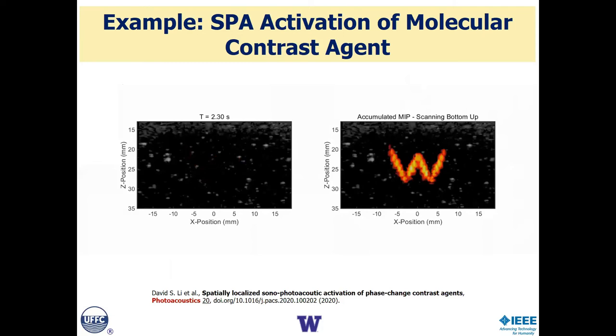I'll just show one image of these types of agents. This is work that comes from our lab in the last year or so, which is a new agent, which is activated with simultaneous light and acoustic excitation. And I won't go into details of the agent. What I will tell you is that this agent can be excited with light levels which are very low, well below a millijoule per centimeter squared, and acoustic pressures with mechanical index well below one, such that we can excite these agents at depths. As you see here, this is about 3 centimeters inside a tissue, and these agents are at picomolar concentration. We can go down to that low concentration. So true molecular imaging done with these nanoscale contrast agents.